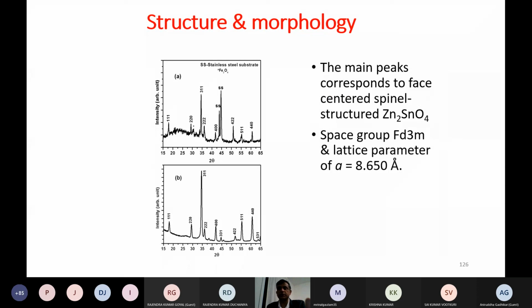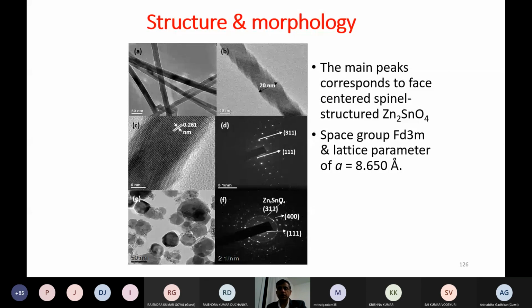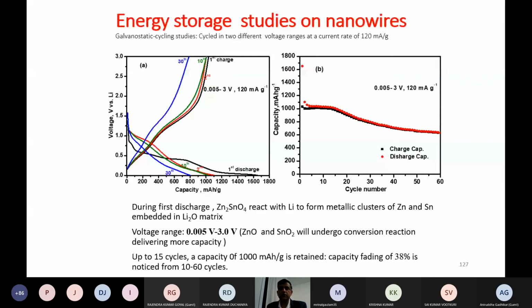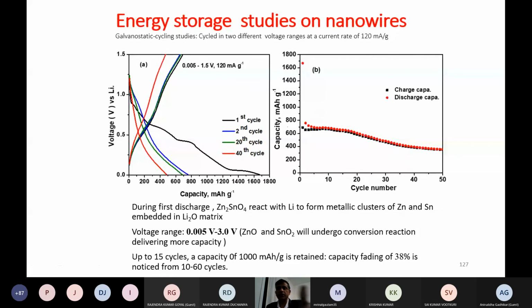Overall summary: these are the expected lattice parameters, and depending on the type, we can retain the nano morphology. Again, the cycled one may become nano or submicron size, etc. So these are the examples. Since alloys work at higher voltage, after a few cycles we can see capacity disintegration. That's why, although many people claim all nano will work, it's not really true. You have to be careful about which voltage you are cycling, and accordingly we can use it for different applications.